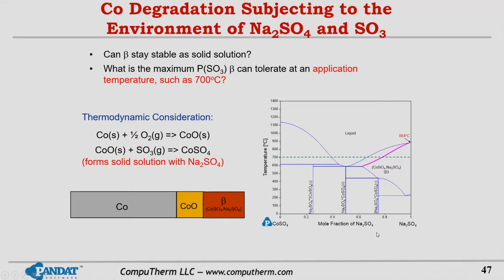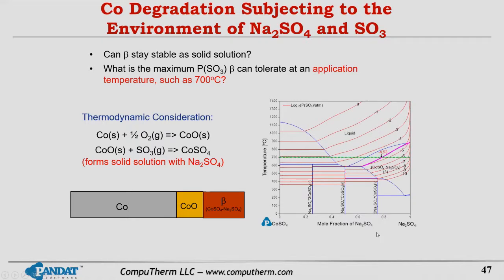From this diagram we cannot tell that, but if we plot the partial pressure of SO3 contour lines onto this diagram, then we can tell that the cross point at 700 degrees and the melting temperature, the partial pressure of SO3 is 10 to minus 4.53. What does this mean? This means if in the environment the partial pressure of SO3 is lower than this value, for example minus 5 or minus 6, then the beta solid solution is stable.